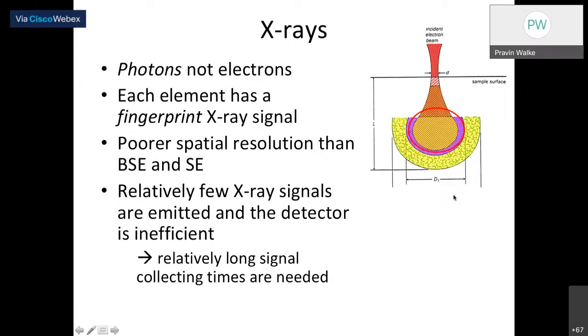Further important is the X-ray, and in X-rays we are not using electrons, we are simply using photons, and those photons can be detected. But the spatial resolution is quite poor in the case of X-rays compared to backscattered as well as secondary electrons, right? Also, these X-ray signals coming from your specimen will take a longer time. Therefore, you have to bombard the electron beam for longer on your sample, and long bombarding time will probably damage your sample, right?